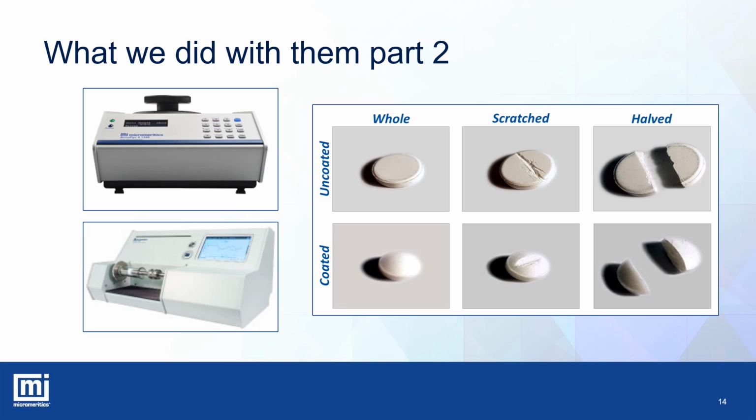We also took uncoated indigestion tablets to act as a control, because we expected to find little or no change in response to the differing levels of damage, as these tablets are just a single component and have no coating layer. So we generated the same kind of data sets, envelope and skeletal volume and density plus porosity, for each tablet type, and we found a lot of what we expected and a little of what we didn't.